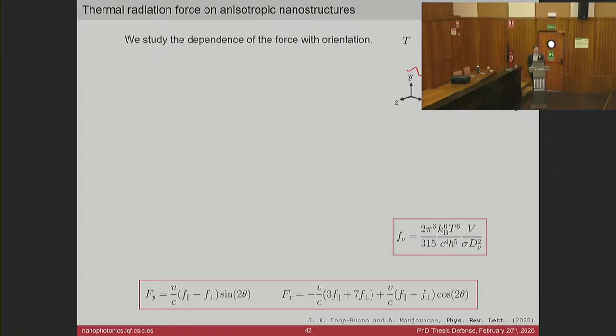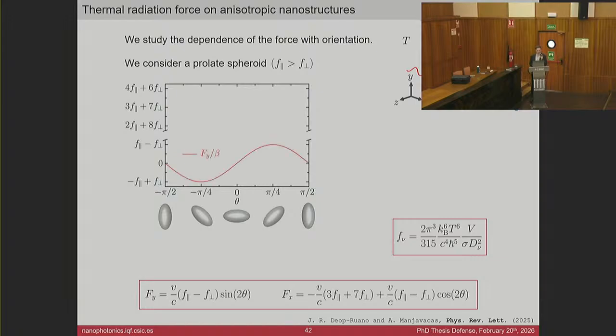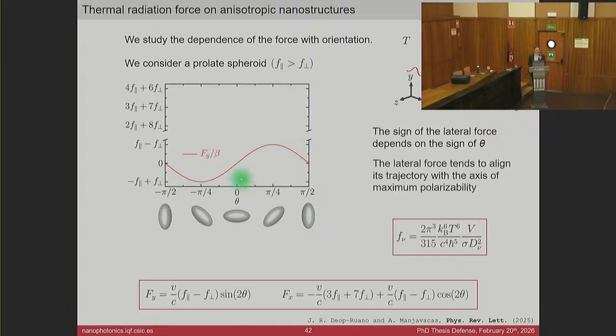So let's study the dependence of the force with orientation. If we plot the lateral force, something interesting we can see is that its sign depends on the orientation of the nanostructure. We can have positive and negative lateral forces. And we can see that it vanishes when the principal axes of the nanostructure are aligned with the trajectory. So we can see that the role of this force is to align the trajectory to the principal axis of the nanostructure. If we now plot the drag force, we can see that it is always larger than the lateral force, but we can optimize this ratio such that they have the same order of magnitude.